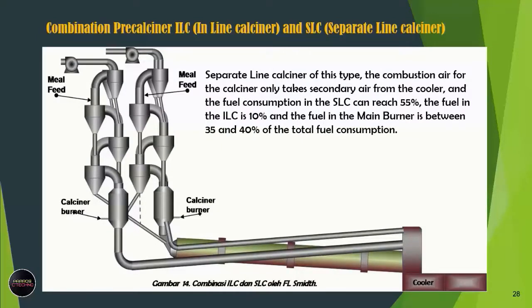Furthermore, this is an image of the combination precalciner between ILC, inline calciner, and SLC, separate line calciner, developed by F. L. Smidth. In the separate line calciner of this type, the combustion air for the SLC only takes secondary air from the cooler, and the fuel consumption in the SLC burner can reach 55%, the fuel in the ILC is 10%, and the fuel in the main burner is between 35 and 40% of the total fuel consumption. Because the use of fuel in the main burner of the kiln is less, the life of the refractory bricks in the kiln is longer than the previous type of precalciner system.